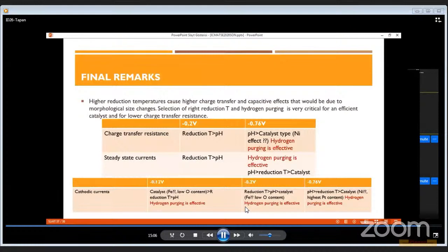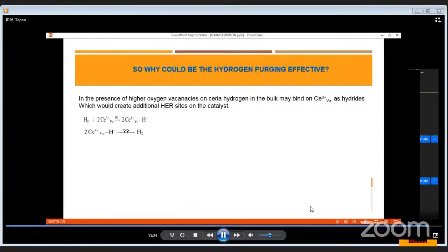High reduction temperatures cause higher charge transfer resistance and capacitive effect that will be due to morphological size change. Selection of the right reduction temperature and hydrogen purging is very critical for efficient catalysts and for lower charge transfer resistance. And as a final word, I'd like to emphasize the importance of hydrogen purging, and would like to give a possible mechanism about what would happen during hydrogen purging.